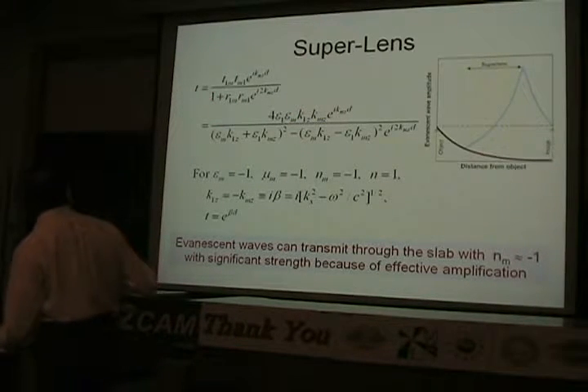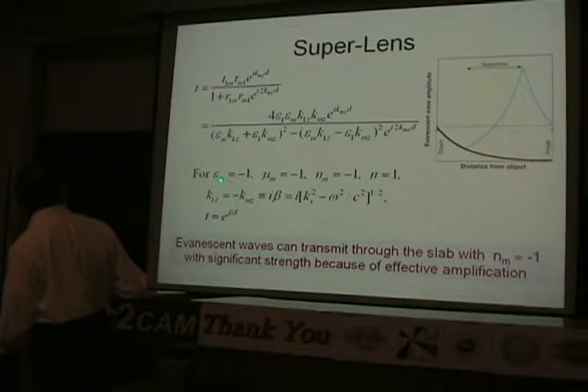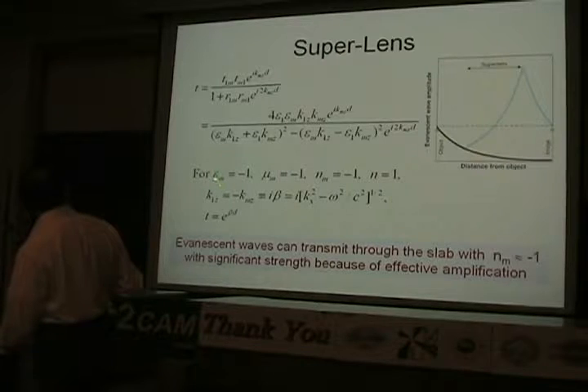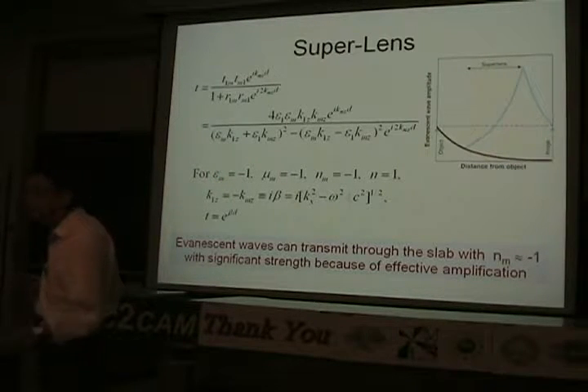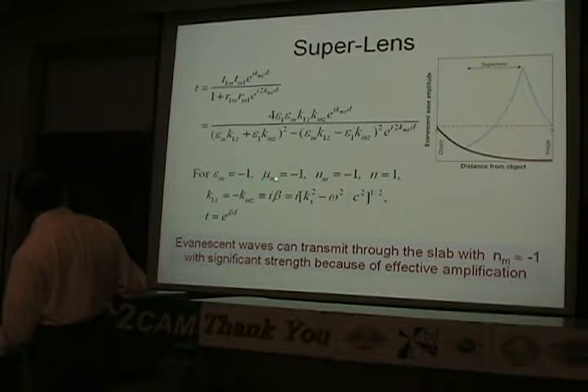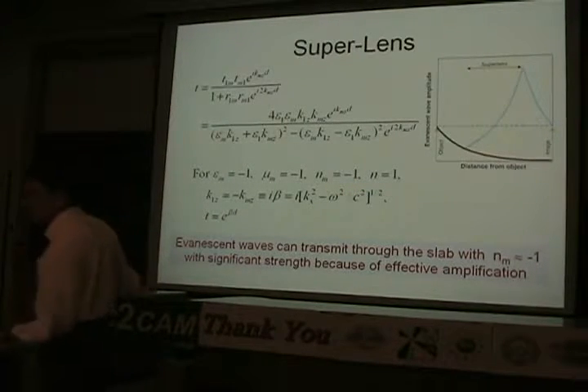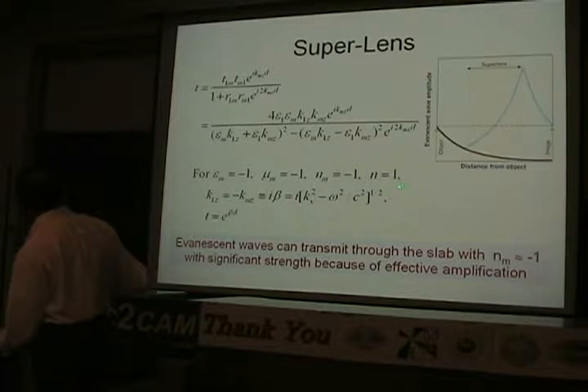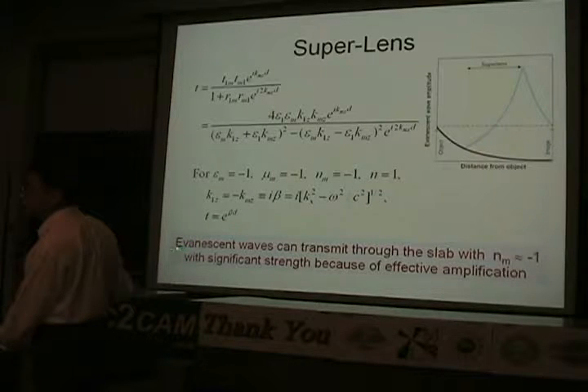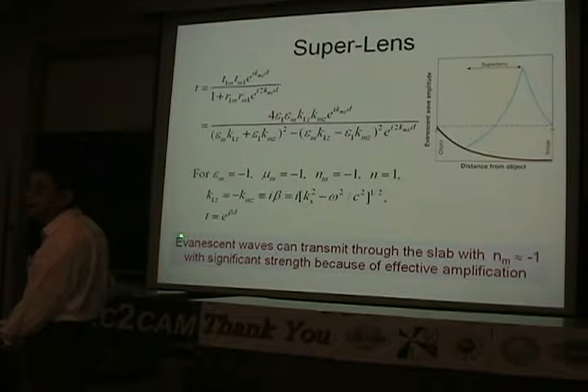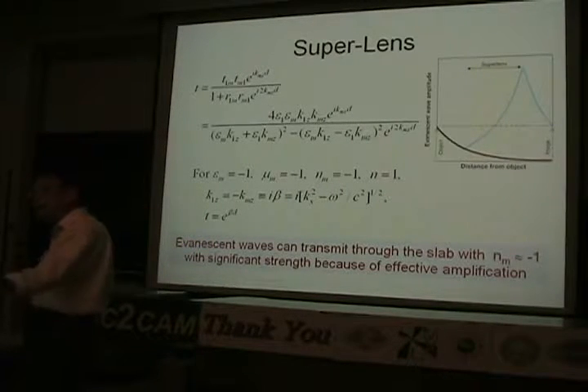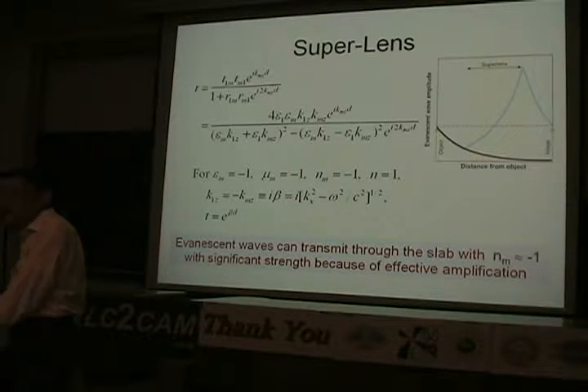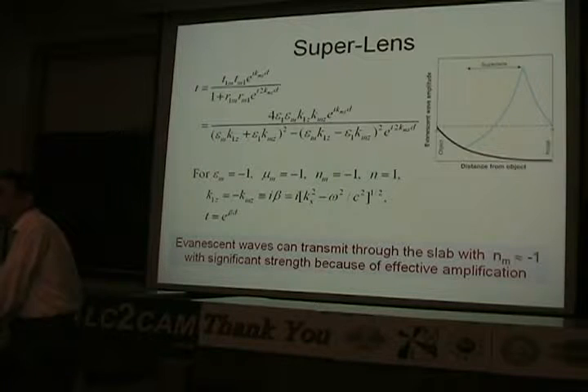Okay. And with this equation, you put in the condition that this middle layer, the slab, has epsilon equal to -1, mu equal to -1, then the refractive index is equal to -1, and the outside is air, and it's equal to 1. Then you can show that this transmission coefficient actually has an exponential growth. So that exponential growth is going to compensate the attenuation of the so-called evanescent wave.